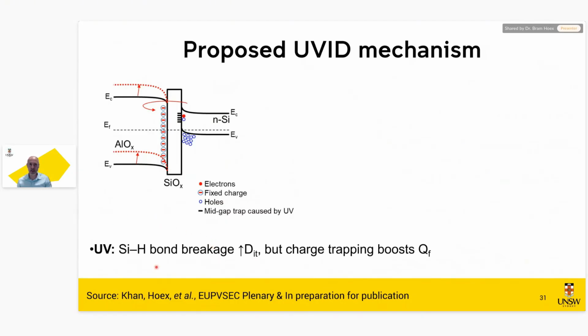So UV breaks silicon hydrogen bonds. This hydrogen piles up at the interface, resulting in an increase in DIT. The UV also increases QF, but the increase in DIT dominates the passivation behavior. So that's why passivation decreases for the typical stacks that we have.